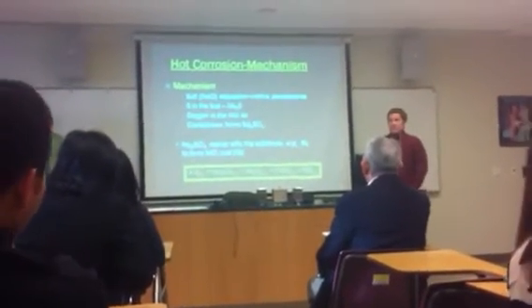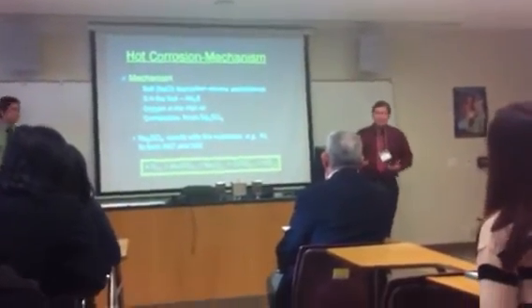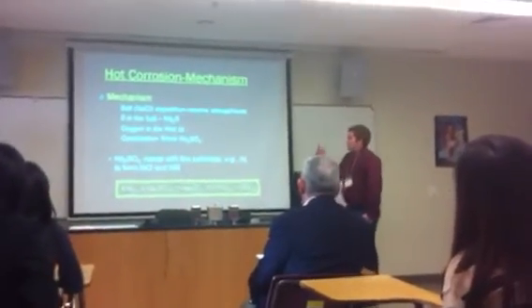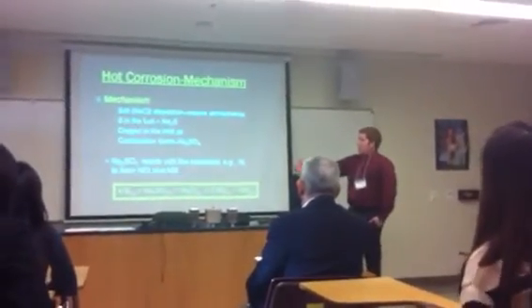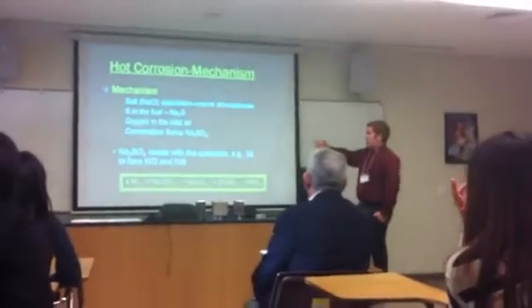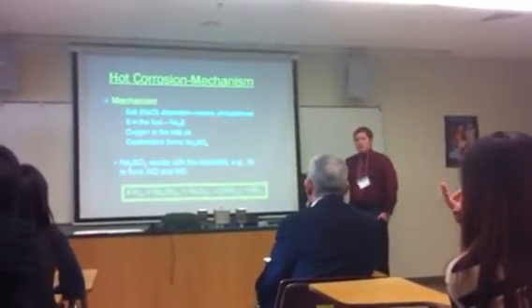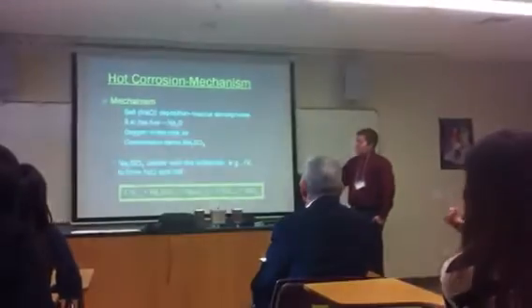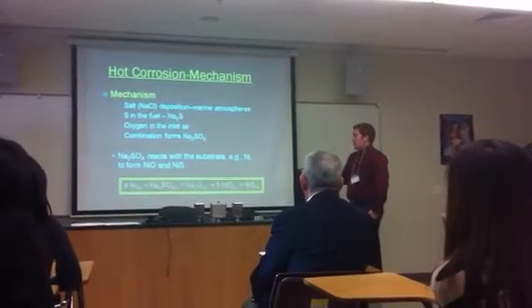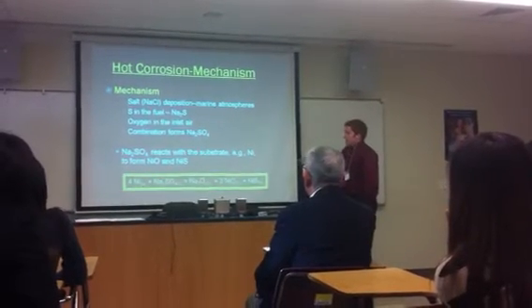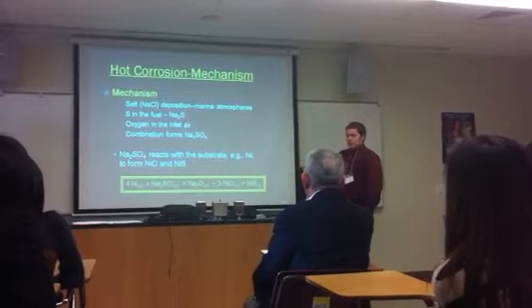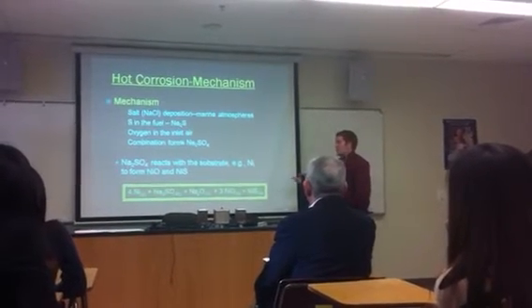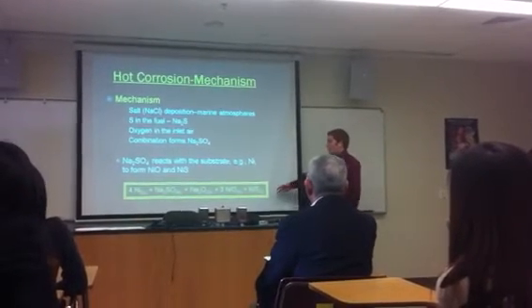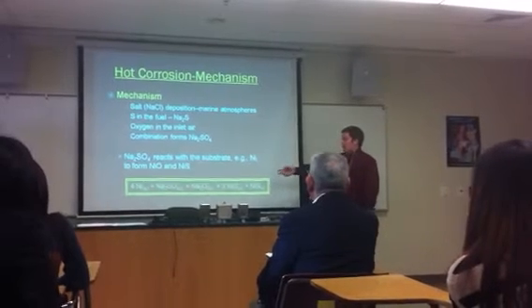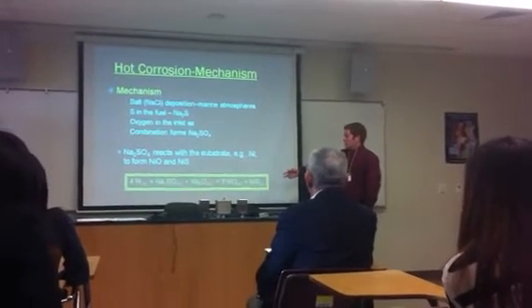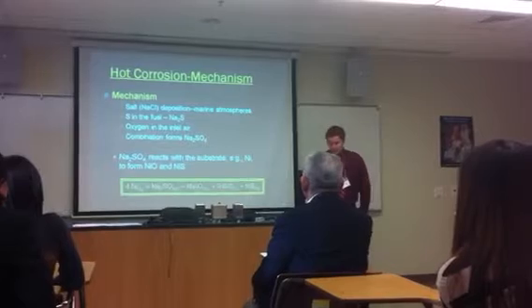And so here's our mechanism. This is how we believe things all come together to create this environment. So you have salt coming in with the inlet air when you're operating in marine atmospheres. The sulfur comes in with the fuel. The oxygen also comes in through the inlet air. And this all combines to form sodium sulfate. This salt, sodium sulfate, then reacts with the substrate, in our case nickel, to form nickel oxide, nickel sulfide. And this equation here is just showing you the nickel reacting with the salt to form nickel oxide, nickel sulfide.